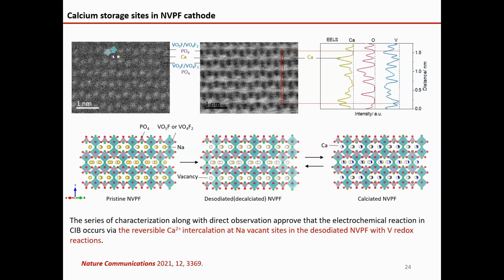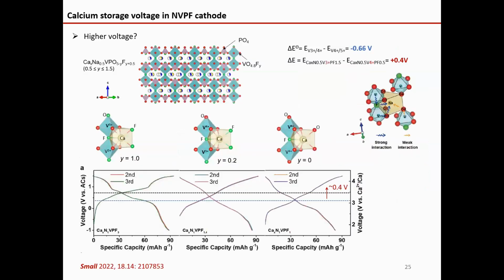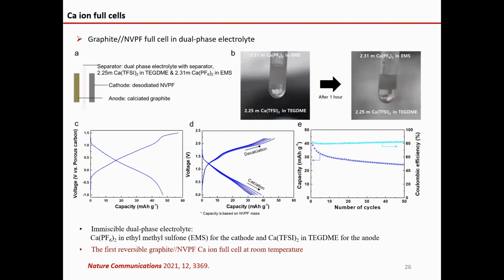So overall, this is a stable host for cathode material, and it can allow high voltage. So we further improve the voltage of the working electrode by introducing more fluoride in this structure by some manufacturing process, because for cathode material, the voltage is very important, which will determine the energy density of a battery.